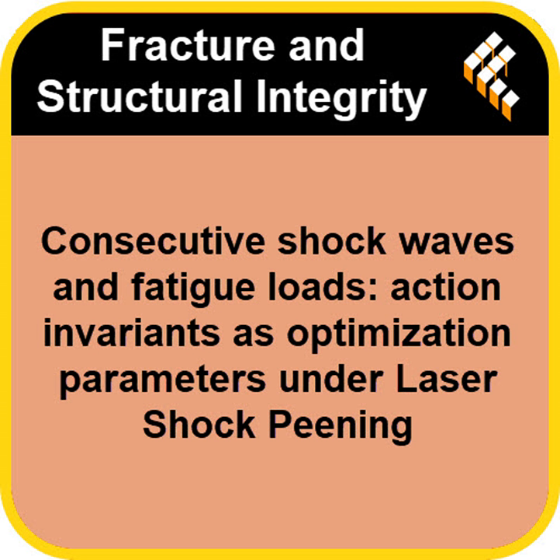Okay, so that gave them the reliable input needed to calculate the shockwave action invariant. Precisely. Then what happened to these shocked aluminum blocks? Did they test their fatigue life? They did. They carefully machined standard fatigue test specimens directly from these pre-shocked targets. So the test samples themselves had already undergone that quantified shock treatment. Correct. Then they put these samples into a VHCF testing rig. We're talking endurance up to maybe 10 billion cycles. 10 billion cycles. How long does that take? Well, they use ultrasonic fatigue machines that run incredibly fast, around 20 kilohertz, so much faster than traditional machines,